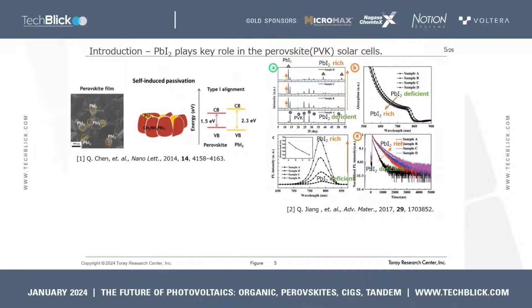X-ray diffraction, XRD, results are shown in Figure A. For sample A, almost all diffraction peaks originated from the perovskite phase. Only a weak PbI2 diffraction peak located at 12.6 degrees was observed. A strong PbI2 diffraction peak for samples B to D confirmed the obvious existence of PbI2, and the diffraction peak of PbI2 is even stronger than that of perovskite for sample D.